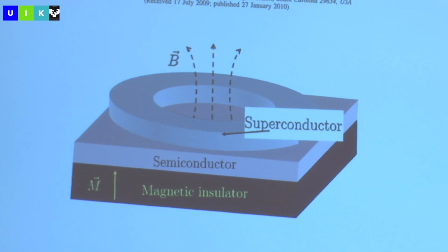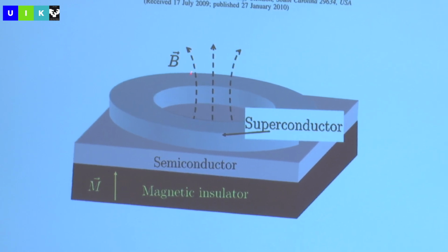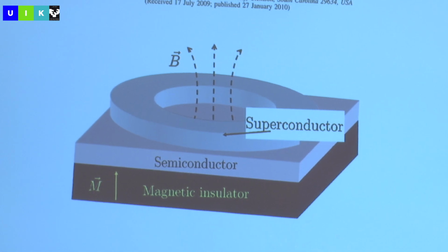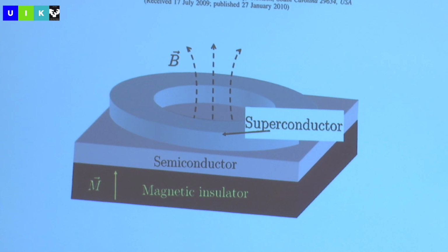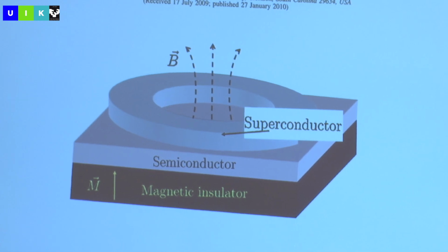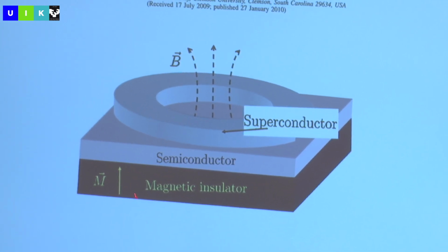Yep. Okay, let me switch topics. Early on in this paper and others published nearby, there was an alternative route to finding topological superconductivity that did not require, and this is again getting back to the red shirt question, the application of a large in-plane magnetic field. It said instead of the large in-plane magnetic field, you can make a kind of pseudo-Zeeman field by using an insulator that happens to be ferromagnetic. And that the scattering of the Cooper pairs off of the surface of the ferromagnetic insulator could Zeeman split them. This was known physics at the time, and I'll show you some of that known physics, but you didn't need to apply a magnetic field. You only needed to scatter off of the surface.